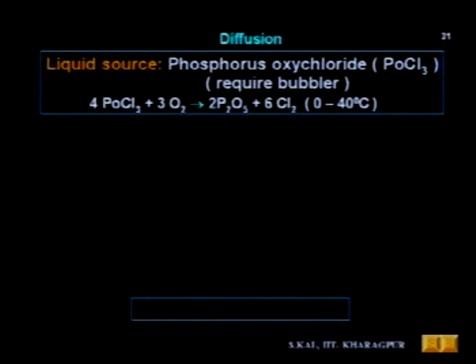Now if we see the liquid source of phosphorus, it is phosphorus oxychloride, POCl3, and the reaction is shown here. This 4POCl3 plus 3O2 again will form 2P2O5 plus 6Cl2, and this reaction can take place even at room temperature, that is within 0 to 40 degrees centigrade. POCl3 in oxygen will form P2O5 and Cl2, and this P2O5 again decomposes to phosphorus, and it will react with silicon to form silicon dioxide, just like the reaction of P2O5 and silicon.